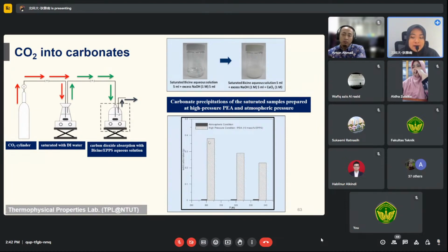So from the high pressure, of course, the CO2 in solid carbonate is higher because the CO2 capture is higher compared to atmospheric. This apparatus we just run in the atmospheric condition. But for the high pressure, we can use the previous equipment like the phase equilibrium analyzer, that's up to high vapor pressure.